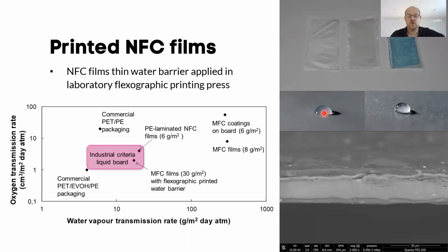The difference when you look at the water drop is quite large. You have the water spreading out on the NFC film, whereas when you have the barrier, you have a hydrophobic surface, a little bit water repellent. What's interesting is that once you let time go, this drop would dissolve into the material while this one would evaporate. The advantage here was that we got a material that could be useful for packaging, just by simple means. We haven't had a chance to follow this one up, but I hope that in the near future we can do something like it.